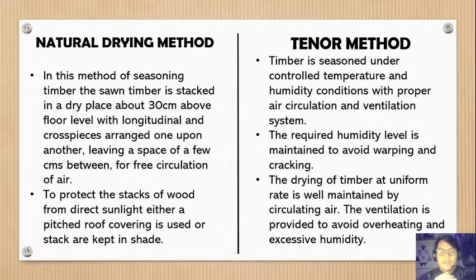Natural drying method. In this method of seasoning timber, the sawn timber is stacked in a dry place about 30 cm above the floor level, with longitudinal and cross pieces arranged one upon another, leaving a space of a few cm between for free circulation of air. Why is this done? It is to protect the stacks of wood from direct sunlight. Either a pitch roof covering is used or the stacks are kept in shade.